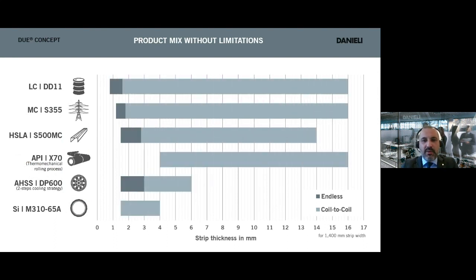By applying this merging, as we mentioned, of coil-to-coil and endless, we have been able to cover, in this example of a possible mix, the lower band of products made in endless, while the thicker band is made in coil-to-coil, in order to select the most economically convenient rolling process mode, because endless is a fantastic tool to play with, but cannot be applied for the whole product range of a quite diversified mix. This goes both in terms of grades, but also in terms of thickness within a single steel grade.